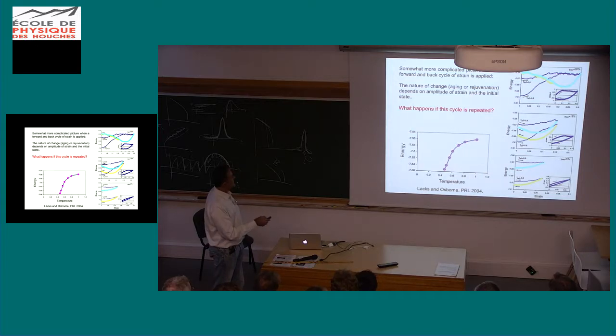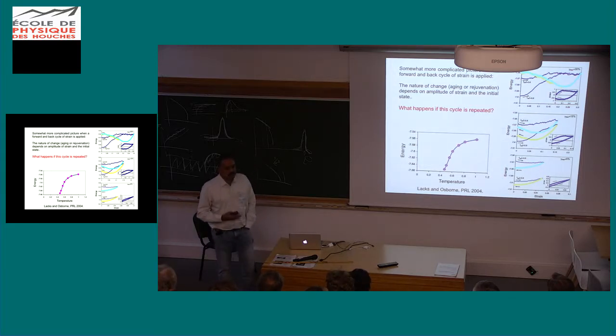A somewhat more complicated picture emerges when instead of just shearing in one direction, one shears back and forth, and this is from the work of Lacks and Osborne. Basically, what energy you end up with when you cycle forward and then back depends on a lot of factors: the initial glass that you start with, how big the amplitude is, etc. So what we began by asking is, if we were to not just do this in one cycle as Lacks and Osborne did, but do it over a number of cycles, what happens?